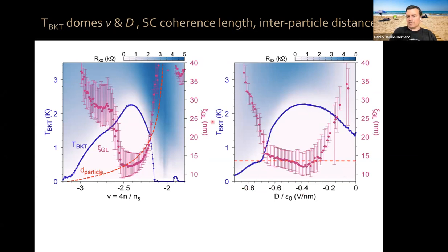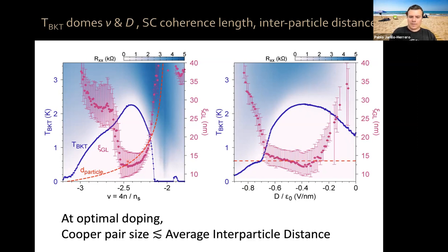Now, the superconducting coherence length in the weak coupling regime, it's giving you the size of your Cooper pairs. It can be interpreted as the size of your Cooper pairs, okay? In a stronger coupling regime as we are here, it's a bound for the size of your Cooper pairs, okay? So this means that at optimal doping, the Cooper pair size is of the same order or smaller than the average interparticle distance, okay?